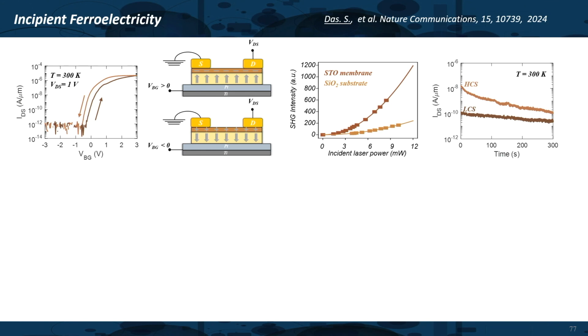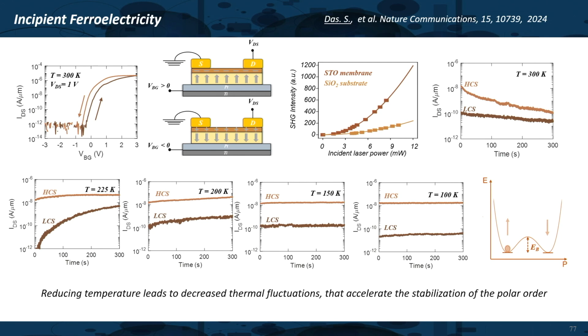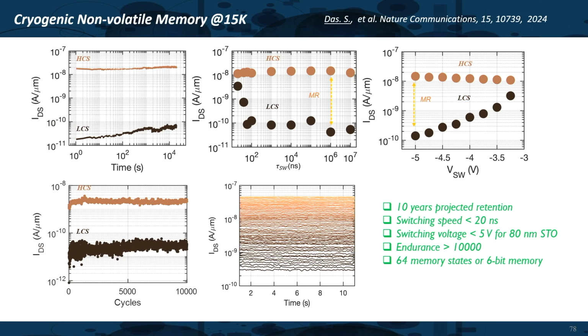But what we found is that when you cool this material down to low temperature, the memory states become extremely stable. So we went out to 100 Kelvin and even 15 Kelvin, and we found that it could be a very good alternative for cryogenic memory, because in a cryogenic condition, charge-based memories may not work as well, and for a lot of quantum applications, you will need cryogenic memory devices. So we went down to 15 Kelvin, and we found that this device is actually an excellent memory device at low temperature with good long-term retention. Switching speed is less than 20 nanoseconds, reasonably fast, and you can also store almost 64 discrete states in a single device. It's almost like 5-bit to 6-bit of memory stored in a single device. So that's also another interesting area that I think is going to be absolutely interesting going forward.